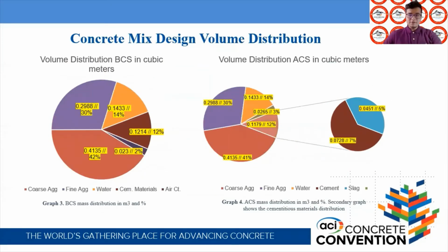Regarding volume, its distribution changed as a consequence of the presence of slag in the cementitious phase. The loss of volume was compensated by increasing the air content from 2.3% to 2.65%. In the following slides, Marco will mention and discuss the results of the alternative case scenario mixture and its benefits and advantages in comparison to the base case scenario.